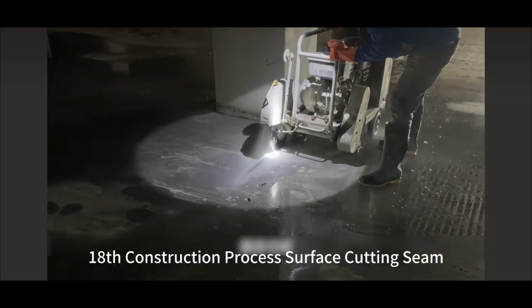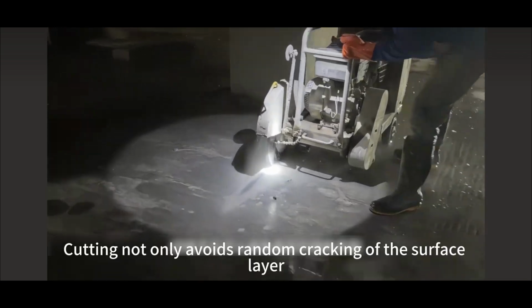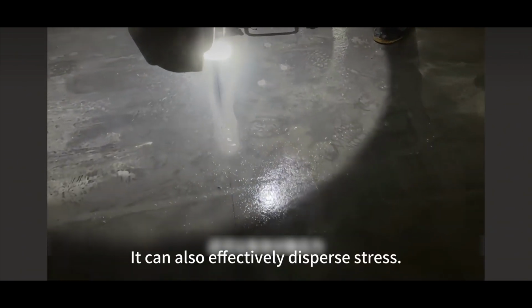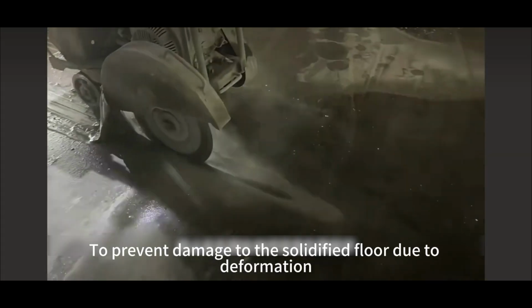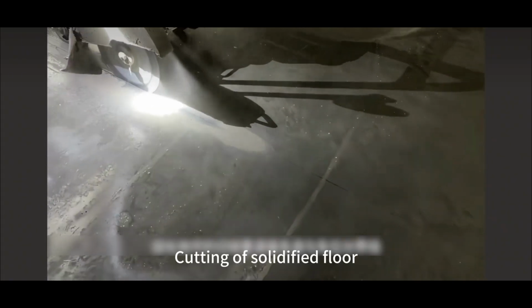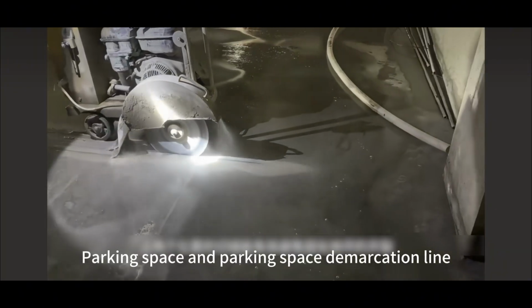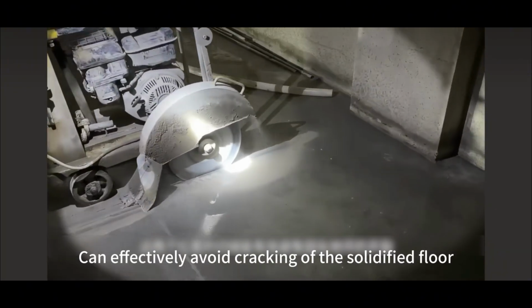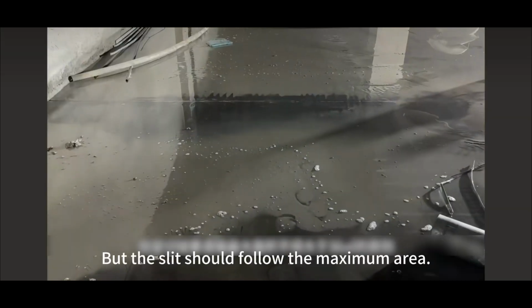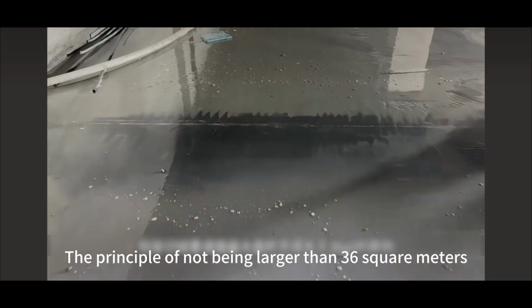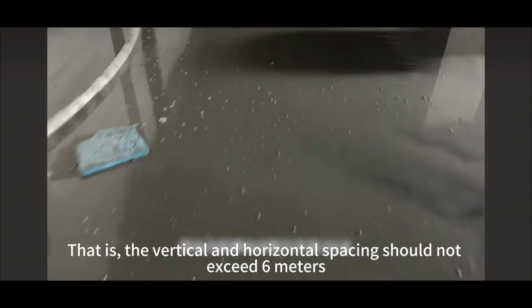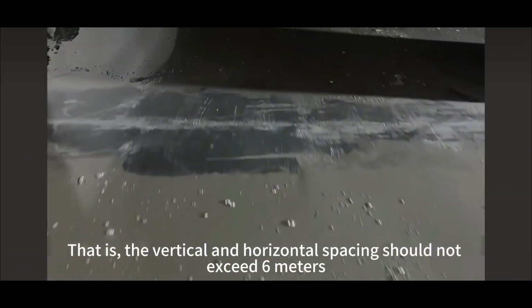Eighteenth construction process, surface cutting seam. Cutting not only avoids random cracking of the surface layer, it can also effectively disperse stress to prevent damage to the solidified floor due to deformation. For cutting the solidified floor, follow the lane line and the parking space demarcation. The slits in these two positions can effectively avoid cracking of the solidified floor. But the slits should follow the principle of a maximum area not larger than 36 square meters, that is, the vertical and horizontal spacing should not exceed 6 meters.